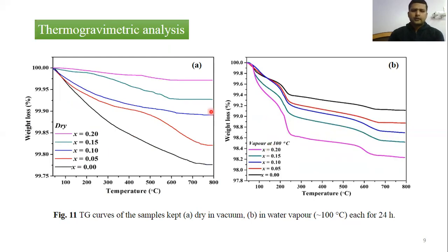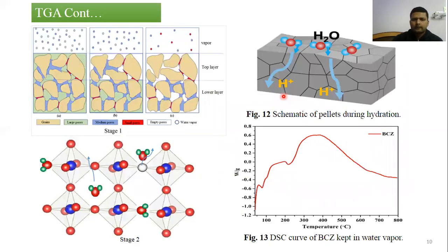Thermogravimetric analysis shows the TG curves of the samples kept in dry and vacuum, and in water vapor, for 24 hours. Here we can see the weight loss around 100 degrees Celsius is mainly due to water in physical form, and that above 200 is due to the loss of water from the lattice site, or structural water.